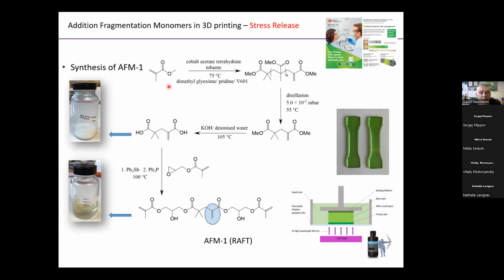We take methyl methacrylate. We now use a very simplified version of the catalyst. So we use cobalt acetate with dimethylglyoxime. So here we make the catalyst in situ because we're not using acids. We distill out the MMA dimer. And we do this in like half a kilo at a time. Then we'll make the methacrylic acid dimer, and then we ring open that with glycidyl methacrylate to give us our RAFT agent, and then we put that RAFT agent into the 3D printer.